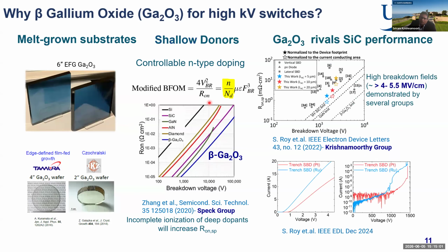And so these are basic ingredients that make the material exciting. But more than that, high electric fields have already been reported in this material. 4 to 5 megavolt per centimeter has been measured by multiple groups across the US, Japan, Europe, and China. This experimentally measured value of electric field in the device is higher than the theoretical field of gallium nitride and silicon carbide. So the high field promise is quite there, and it's been seen by multiple groups. I think these ingredients make it exciting to work on this new material system, to develop the material science, growth, and try to make a nice high voltage vertical power switch. That's been the focus of my group.